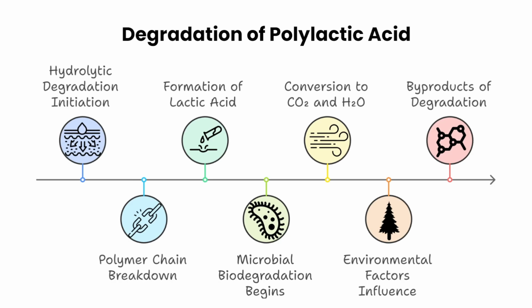In industrial composting, under controlled conditions with high temperatures, moisture, and microbial presence, PLA can fully degrade within 2 to 6 months. However, in natural environments such as soil, marine ecosystems, or lower temperature conditions, PLA degrades much more slowly, taking years or even decades. Additionally, acidic or basic conditions can accelerate hydrolysis by catalyzing the breakdown of ester bonds.